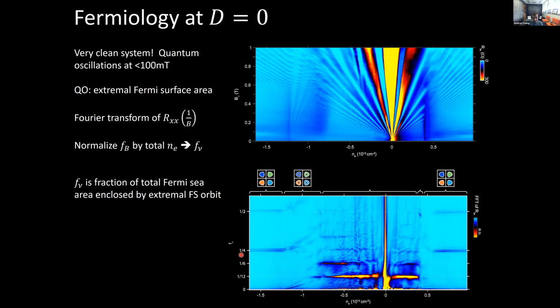But now as we lower the density on the hole side, you see that this frequency starts to go up, and it's joined by a very low frequency oscillation that starts from 0. And that's, again, exactly the behavior you expect if you're nucleating an annular Fermi surface, so you've nucleated now an opposite charge Fermi surface. Now the difference between these 2 frequencies is going to add up to 1/4 because you still have 4 of them, and so on. Then there's more complexity. At very low density, you actually see a strong peak at 1/12 of the total, and you can tie that to these 3 pockets in each of 4 flavors.